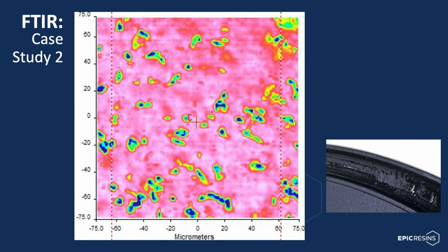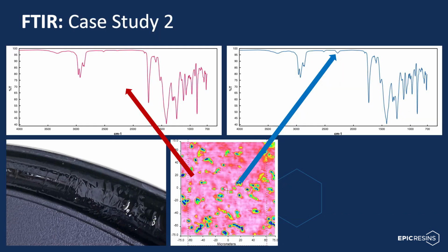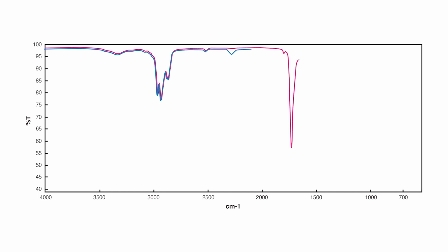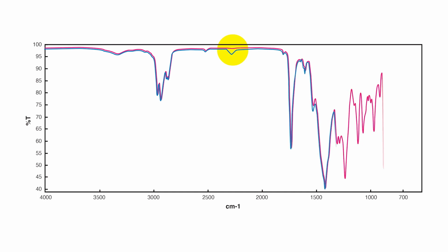You will probably notice the significant color variation in this example compared to the first example. This is because the ATR microscope uses color variation to visually show where there are significant variations in the FTIR spectrum. If we look at the spectrum of the pink areas, you can see at 2275 inverse centimeters, the absorbance is minimal. However, the spectrum of the blue dots show a distinct peak in this region. To compare these regions, we superimpose the spectrum absorbance of the blue dots onto the spectrum absorbance of the pink areas. You can see a distinctly different peak at 2275 inverse centimeters.